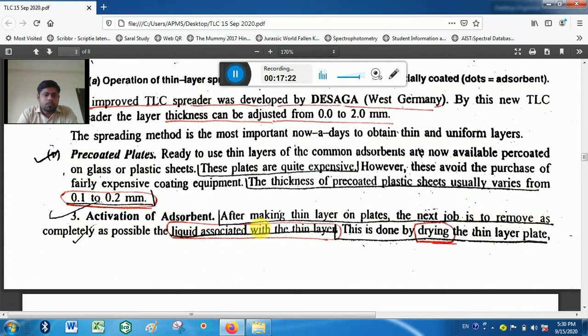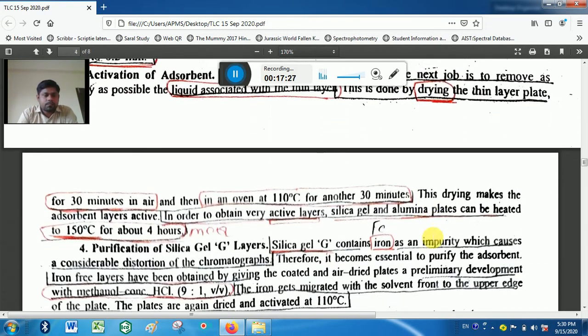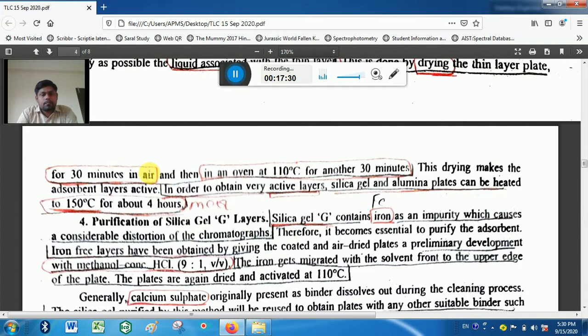They must be removed, and that is done by drying the thin layer plate for 30 minutes in the air, or then in an oven at 110 degrees Celsius for another 30 minutes. That means when you apply the slurry or suspension on a plastic sheet or a glass sheet, let it dry for 30 minutes in the air and then 30 minutes in the oven at 110 degrees Celsius. That way the solvent in which you dissolved your adsorbent is removed, and your layer becomes very dry, and it is used as a TLC plate.